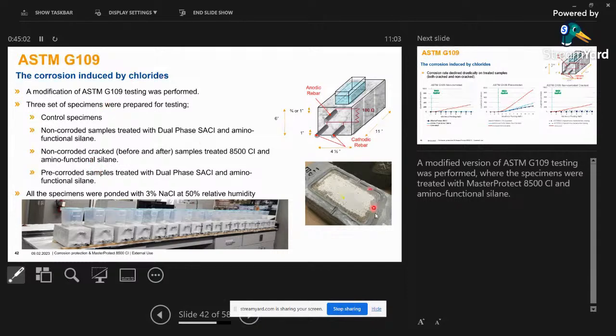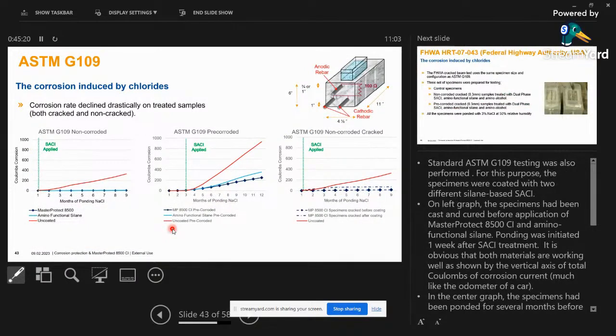Now, if you look at this test which was done to assess the effect of chloride induced corrosion. So there was 50% relative humidity, 3% NaCl solution. The specimens were ponded with such a high chloride based solution, and you will see that this is a control sample which is uncoated. All of this is uncoated. So you will see in non-corroded cracked concrete how the... What you see here is MP8500CI. It's a proprietary product, but not going into that. It is being compared with amine functional silane and other technologies.